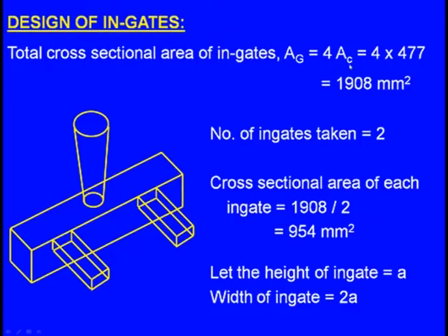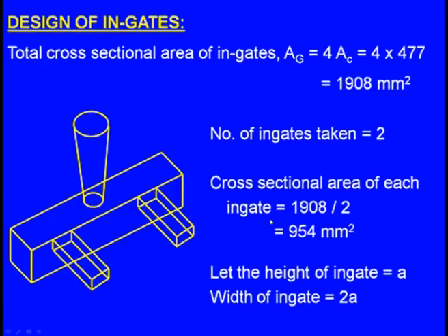Now, we need to design the ingates. The total cross sectional area of the ingates, AG, is equal to 4 into AC, that is equal to 4 into 477, which is 1908 square millimeters. In this case, we are taking two ingates. The cross sectional area of each ingate is equal to total cross sectional area divided by 2, that is equal to